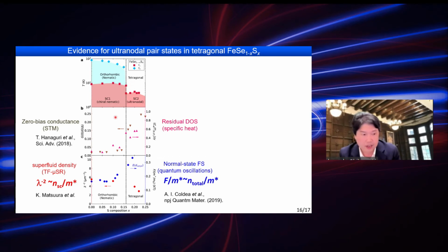From the zero bias conductance measured by STM, shown by this brown data, and residual density of states from specific heat, shown by pink, they both show that zero energy states suddenly appear when you enter the tetragonal side of iron selenium sulfur.